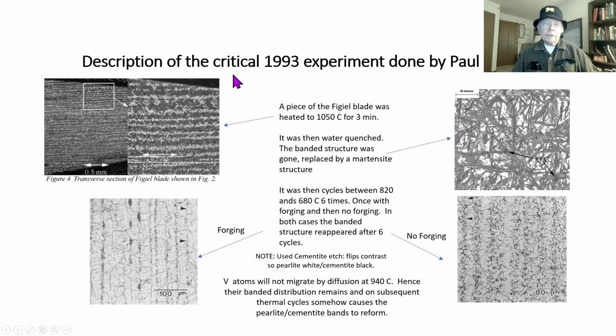Now, here's a description of a critical experiment done by Paul in 1993. We took a piece of Figiel blade, heated it to 1050 for 3 minutes, and that's what it looked like after we quenched it in water. The bands were all gone, and we're just left with that martensite structure. We then cycled it between 820 and 680 C 6 times, once with forging during the 6 cycles, and once with no forging. And this is what we find.